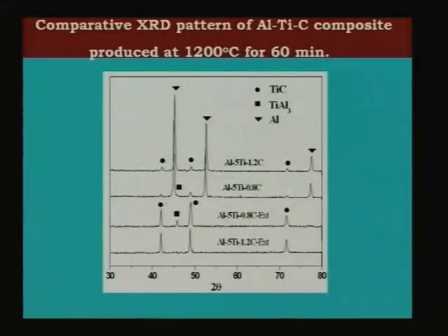So, if you look at these aluminum TiC composites, one with 0.8% carbon, another with 1.2% carbon, you can see the presence of TiC particles very clearly in the 1.2%, and if you take these two composites and dissolve all the aluminum matrix and look at those extracted particles carefully, you will see the 0.8% carbon extracted particle shows you both TiC peaks and TiAl3 peaks. Here you cannot see those TiAl3 peaks because the volume fraction of TiAl3 in this is very small. So, if you take the whole composite and subject it to XRD, you can see that TiC itself is how much?